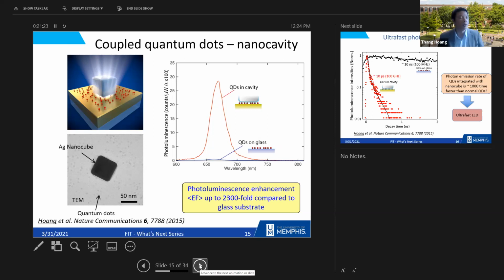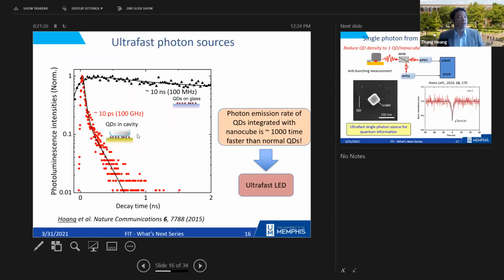like I said before. And then we can also measure the decay time from these quantum dots. This is the intensity versus the time it takes for the photon to get out of the quantum dots. In this case, for the quantum dot on the glass without a nanocube, you see around 10 nanoseconds. And for the quantum dots on the cavities, you see that the decay time is about 10 picoseconds. So you see that it is 1,000 times faster.